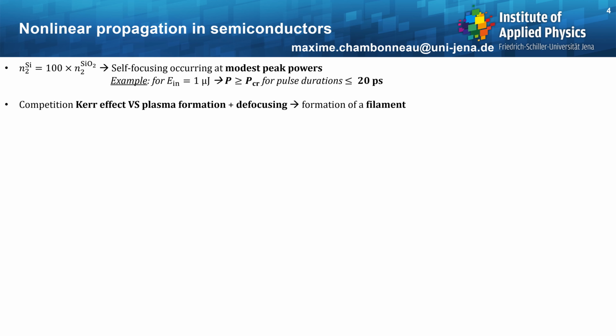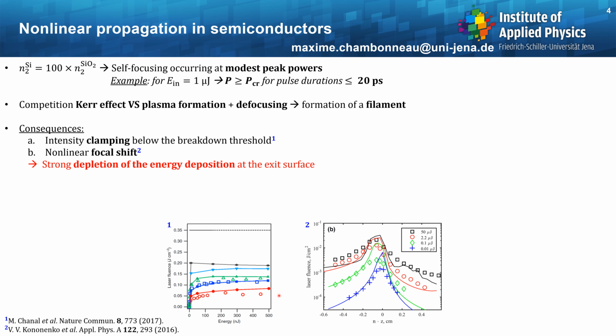If we want to answer this question, we have to keep in mind that silicon is a medium where the propagation is extremely nonlinear. And this originates from the nonlinear refractive index of silicon, which is about 100 times higher than the one of fused silica, for instance, meaning that self-focusing will occur at relatively modest peak powers. This implies that there is a competition between Kerr effect on the one hand and plasma effect on the other hand. In other words, a filament is formed, which has two major consequences. First, as illustrated here, there is a saturation of the intensity reached inside silicon below the breakdown threshold. Second consequence, as illustrated here, there is a nonlinear focus shift. And taken together, those two consequences lead to the conclusion that there is a strong depletion of the energy deposition at the exit surface of silicon.